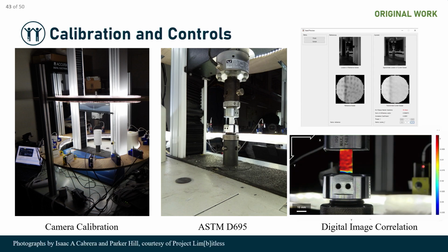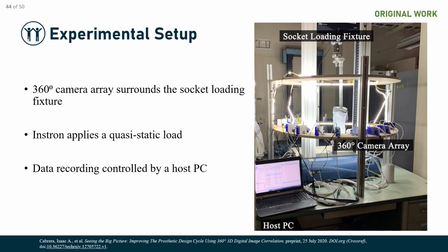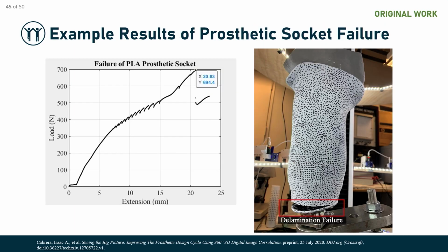And so what does this allow us to do? It allows us to do this technique called digital image correlation, where if you have these spots on the surface of an object, known as speckles, you can track that pattern over the course of a deformation cycle and analyze what the strain or the displacement is on the surface of a sample. And so we built a system that could do this digital image correlation in 360 degrees all around the surface of a prosthesis. And that's what you see here on the right in this load frame. This is just showing how our test specimen in this case failed. It's a delamination failure at the bottom.